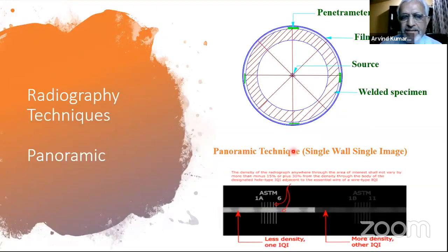Then another technique is called the panoramic technique. This is used for big size pipes, like a 20-inch pipe or even a bigger size, 64-inch pipe or larger diameters also, where you place the source in the center of the pipe where you have a weld, and then you place the film outside all around, and with a single exposure the entire circumference of the weld is getting exposed. So that is called a panoramic technique.